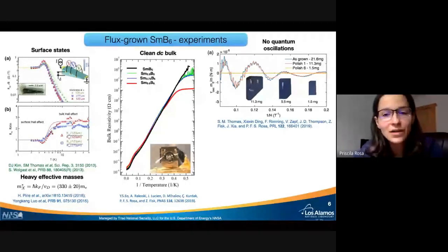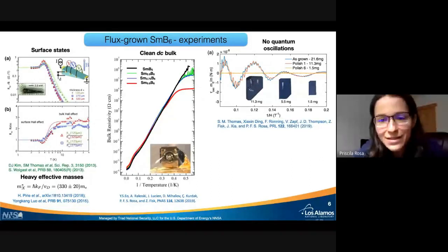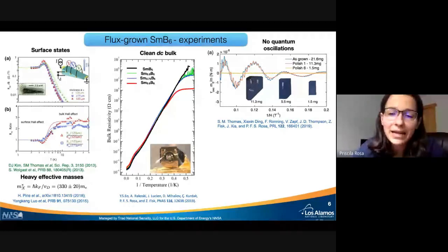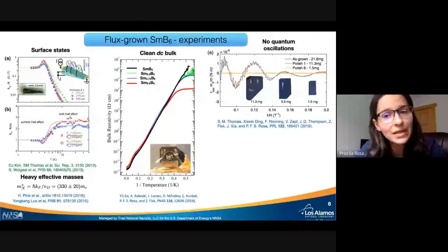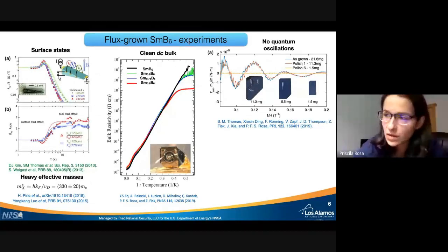So you can see here in the figures of the samples, it almost looks like a smiley face, right? Smiling at you. But those aluminum deposits, unfortunately, again, generate quantum oscillations that are not intrinsic. So we strongly believe that quantum oscillations are not present in these crystals. And perhaps for the students in the audience, this was actually a negative result that was very unfortunate.